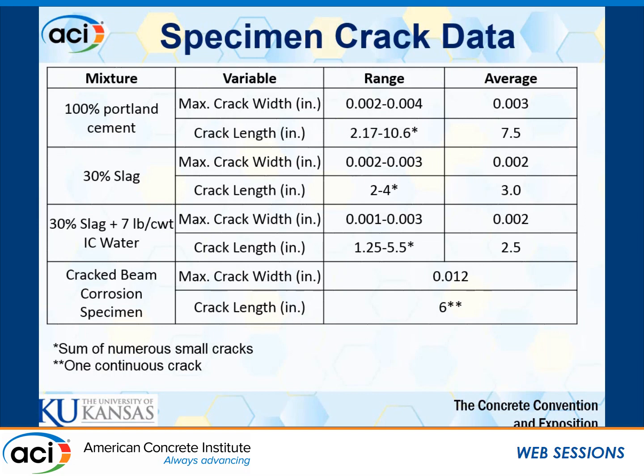We see a significant decrease when we use slag and internal curing, with that average crack length dropping quite a bit and even that width dropping from 3 mils down to 2 mils. And just for reference there at the bottom, we have our cracked beams, which is just our 12 mil wide stainless steel shim, 6 inches long.